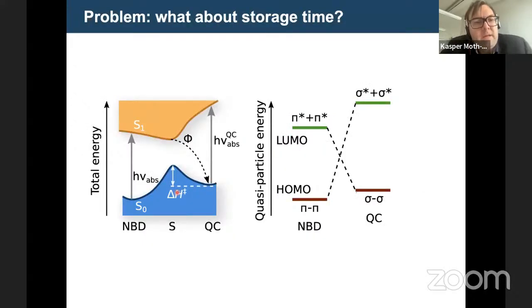So how can we do that? If we look at the energy landscape again, we want to achieve two things. We want to have the absorption as low energy as possible, and we want this energy barrier to be as high as possible. And the problem is, you can see it here, that this barrier is more or less at the crossing point of the two different surfaces, the pi star interacting with the pi, and the sigma star interacting with the sigma. And the crossing point is more or less where the height of this barrier is. So if we bring down the HOMO-LUMO gap, this barrier will also go down.